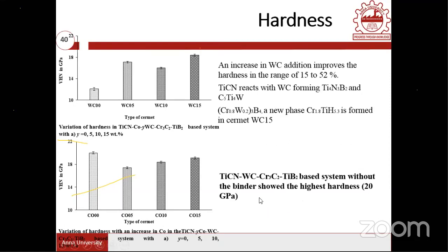And also the tungsten carbide addition. So the tungsten carbide addition basically improves the sinterability, and also it improves the hardness value. It is close to 20 GPa. It's nearing that value. So 15 to 52% of improvement. And also some other new phases were formed. Those are the phases responsible for hardness improvement.